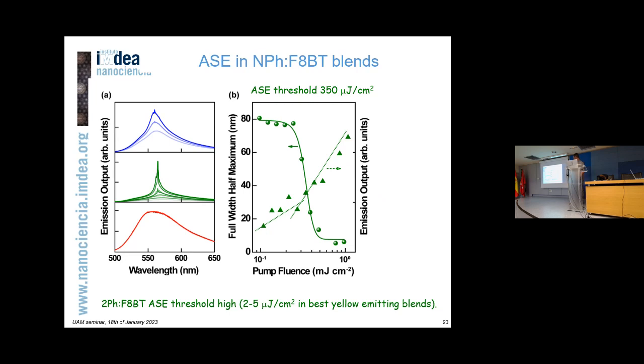What you have here is basically fluence plots of the emission linewidth as a function of fluence, showing how narrowing takes place and how the emission undergoes a change of slope above the threshold of amplified spontaneous emission. So it worked, but only for blend 2. And then the question was why it works for blend 2, not for blend 1 or 3.